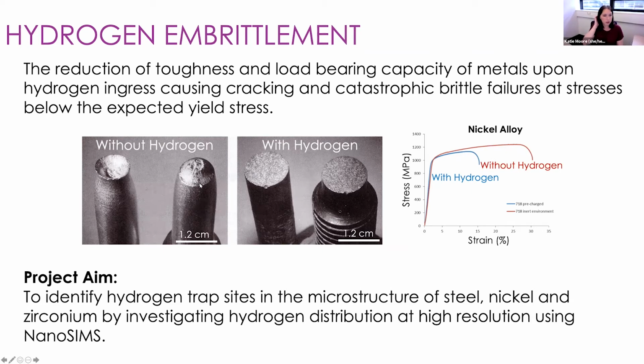So the aim of these projects that I'm going to talk about today was to identify where hydrogen is being trapped in the microstructure of steel, nickel, and zirconium alloys by investigating the hydrogen distribution at high lateral resolution using the NanoSIMS. Because although we know the hydrogen is there and we can see the effects of it, we don't know exactly where it is located in a lot of cases.